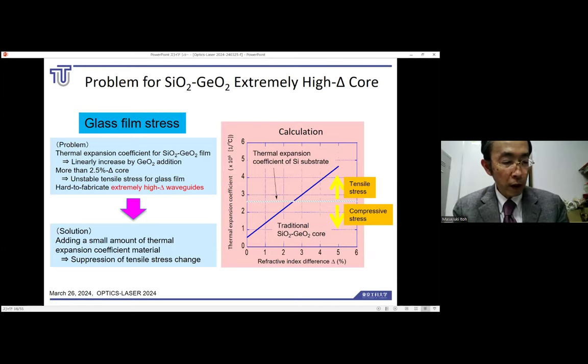To start, I will discuss the problems in fabricating extremely high delta waveguides using germanium dioxide material. Silicon dioxide, germanium dioxide waveguides are in common use today. One major problem is the stress of the glass film. The thermal expansion coefficient of the silicon dioxide, germanium dioxide film increases linearly with the germanium dioxide content of the material.